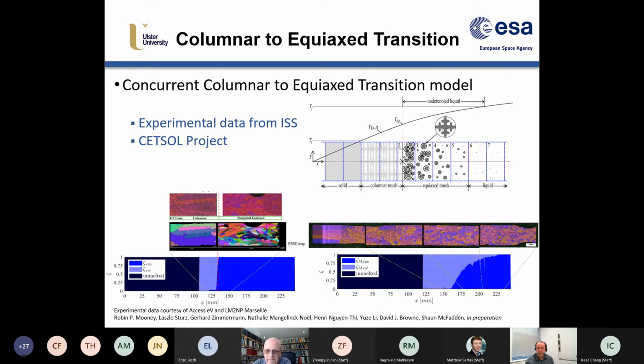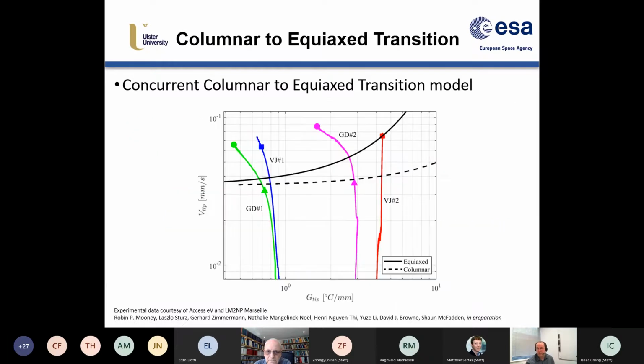And then when we compared that, if you look at the extents and try to map against the different positions, I think the agreement is reasonably good. There were 4 experiments done in total, and we were able to take the information from the simulation, the tip rate, the tip growth rate, and the temperature gradient at the solidification front, and map this onto a Hunt diagram.